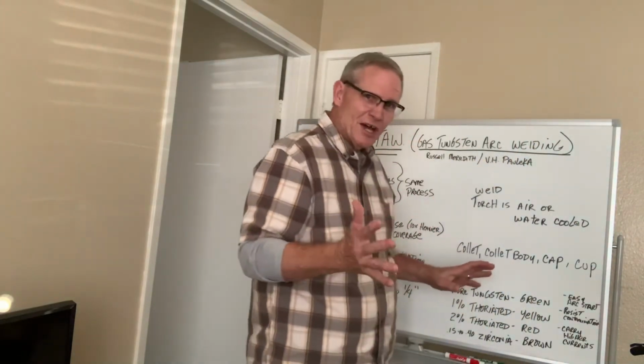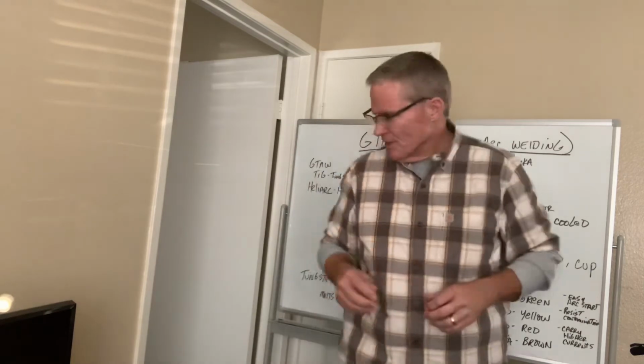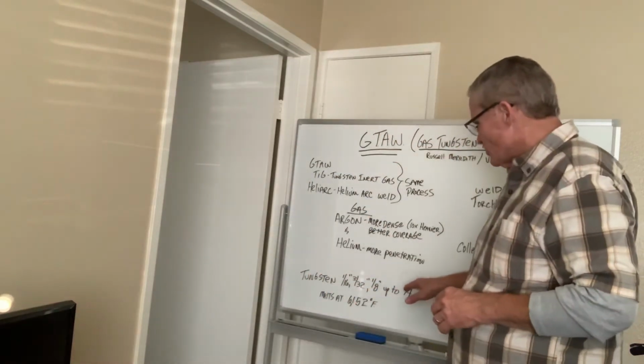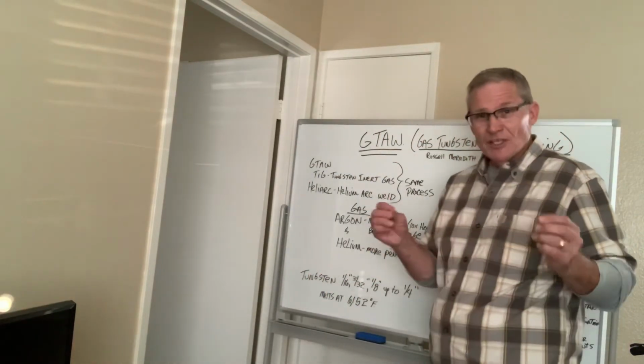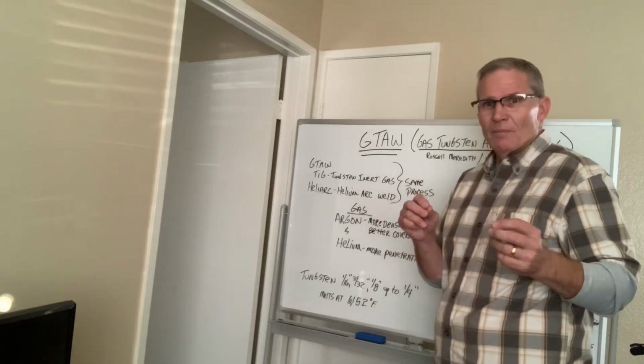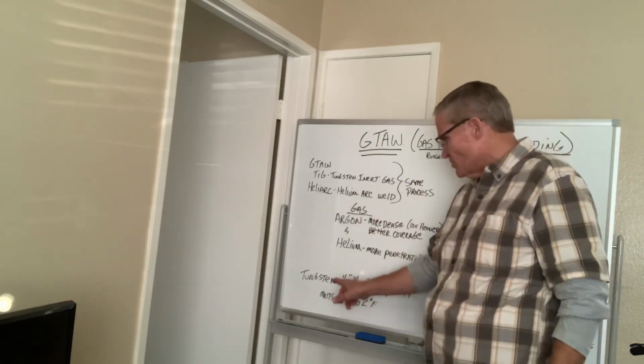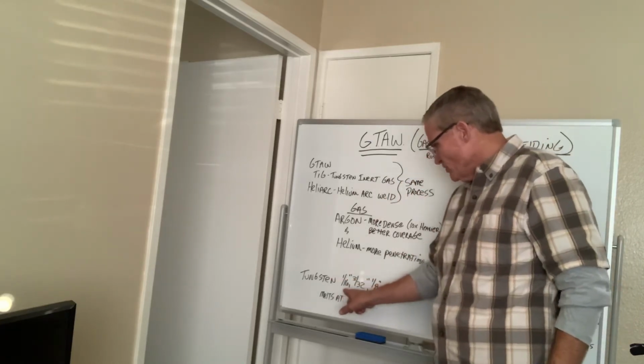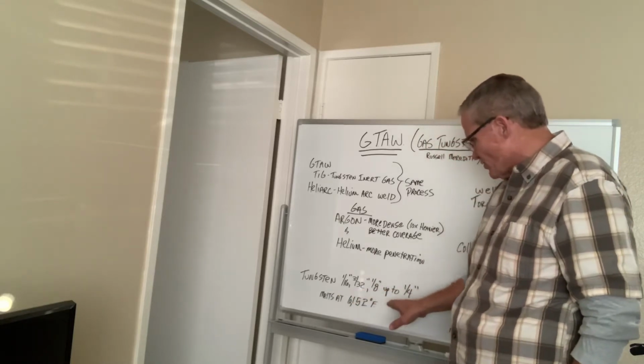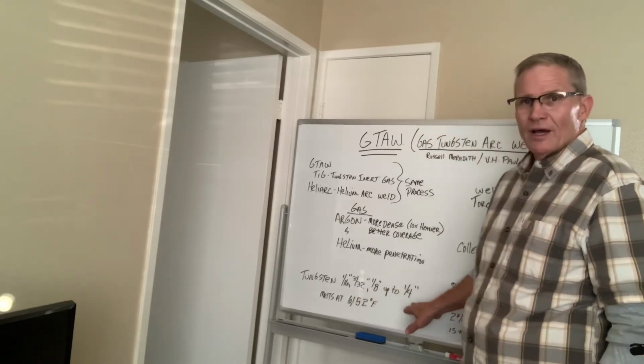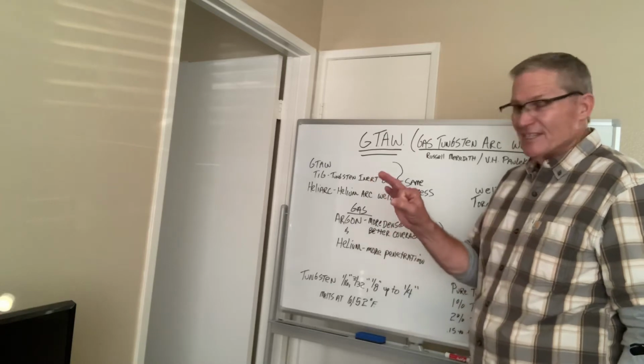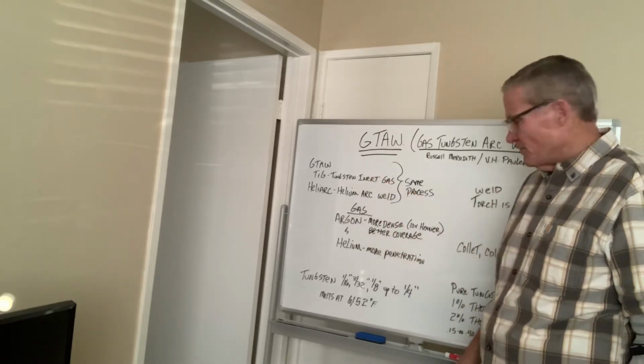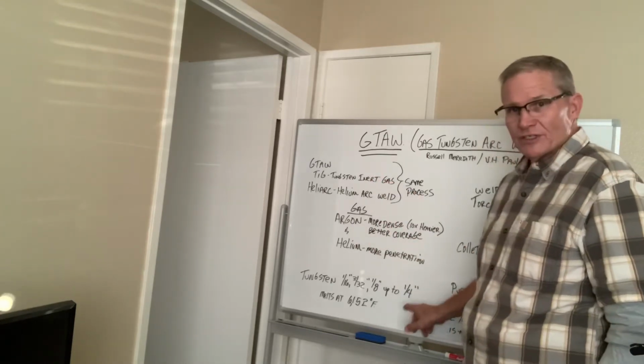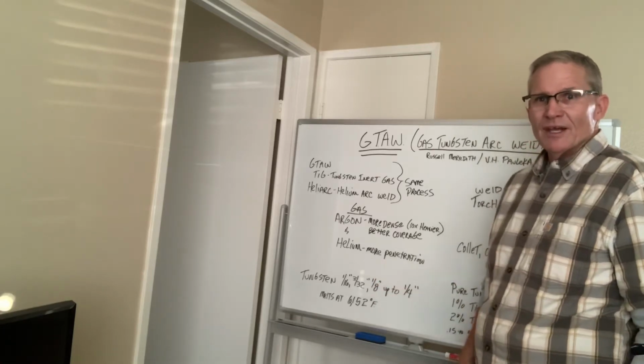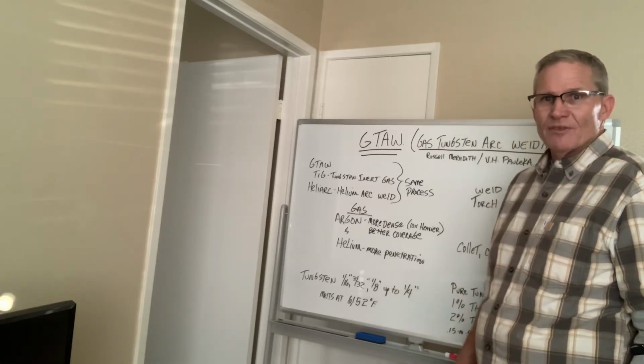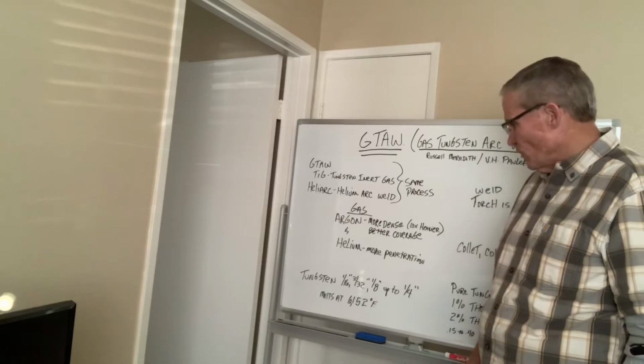We can talk about the tungsten for just a moment. The tungsten comes in different sizes. Again, make sure the collet and collet body are the same size as whatever tungsten you have. And there's 1/16, 3/32, 1/8 inch, all the way up to 1/4 of an inch. And I'm talking about the diameter of the tungsten itself. You can imagine a 1/4 inch in diameter piece of tungsten. You'll be able to weld some fairly thick pieces of material with it.